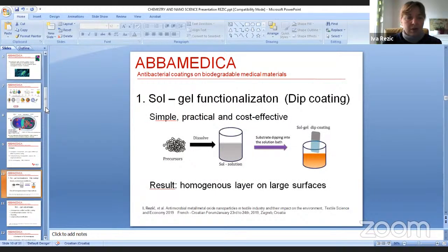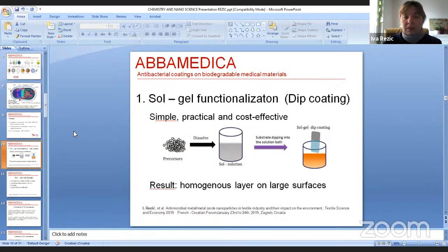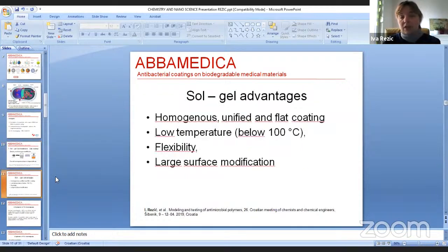The first step in our laboratory is to prepare the polymer material coated with nanoparticles. For this, we use a sol-gel functionalization methodology, also called dip coating, in which we mix different chemicals with nanoparticles in solution, and then our polymer is dipped in and slowly pulled out in order to obtain a homogeneous layer on large surfaces. This procedure has many advantages because we can produce a homogeneous, uniform, and flat coating. The temperatures that we use are rather low, below 100 degrees Celsius. It is a very flexible method, and we can modify really large surfaces.